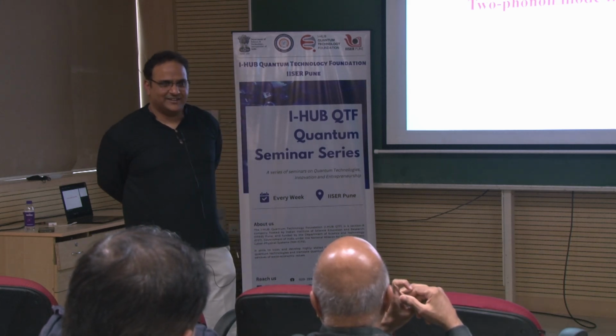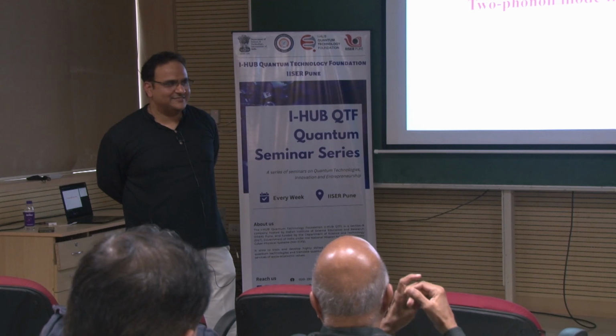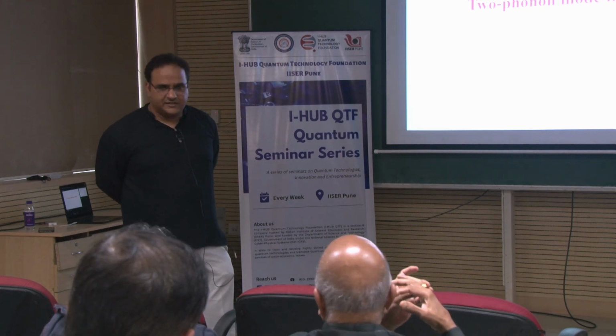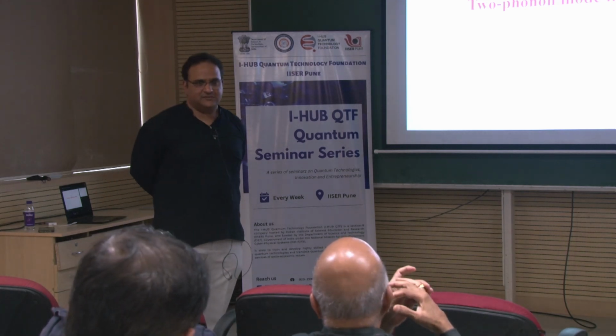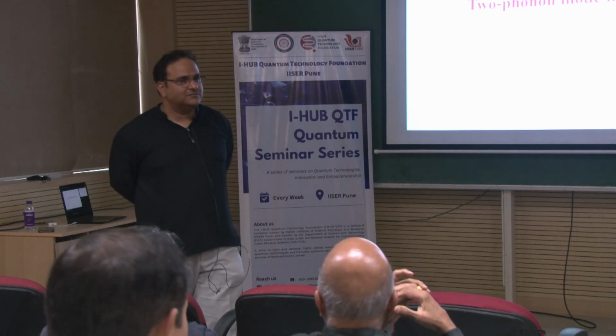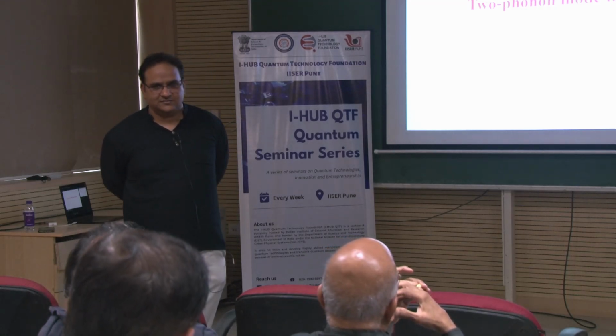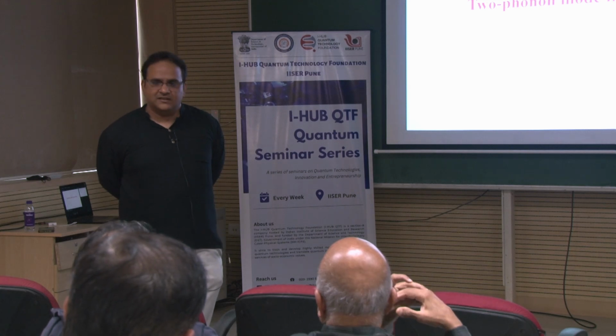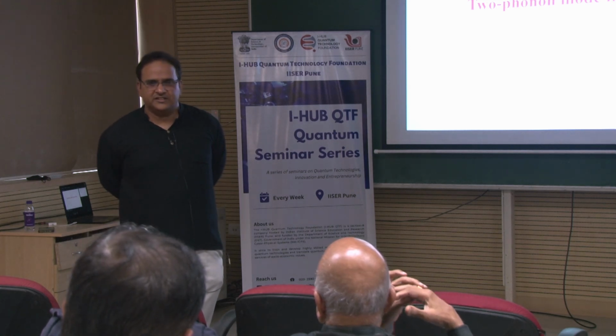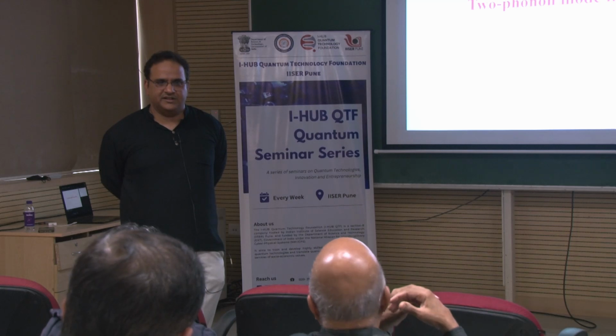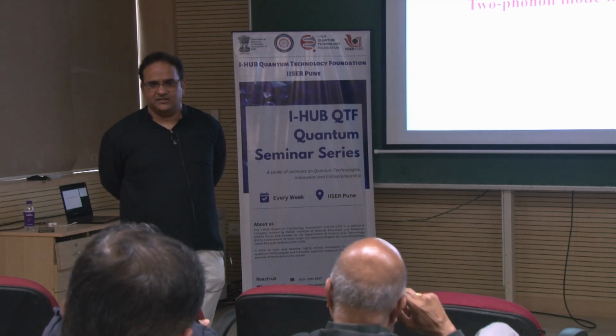I'll get back to you. There would be some influence. So you can cool your sample down to 2 to 3 Kelvin, in the Montana. And there's no self-heating, I mean laser heating. Before taking the spectra you do a power dependence at low temperature and high temperature, because you know that's a serious issue.